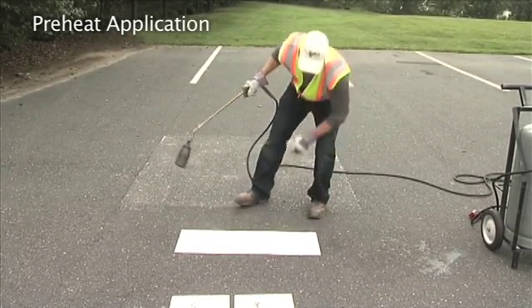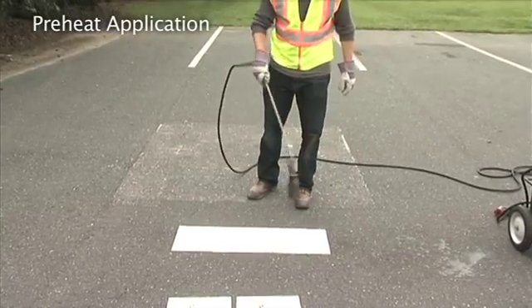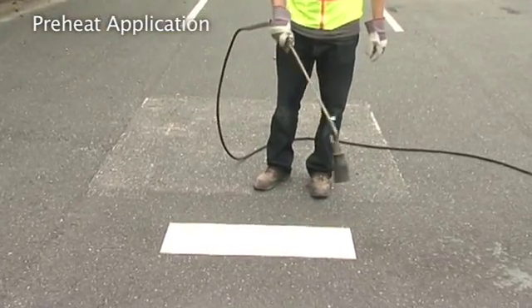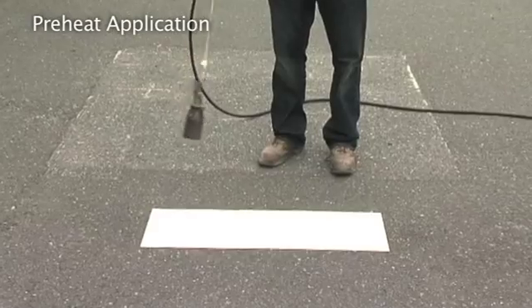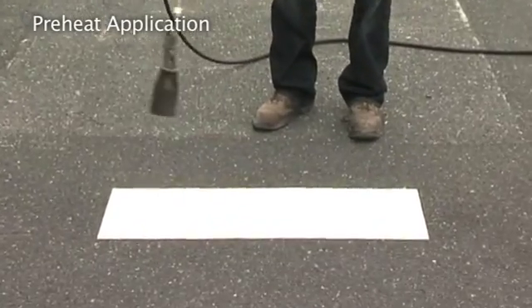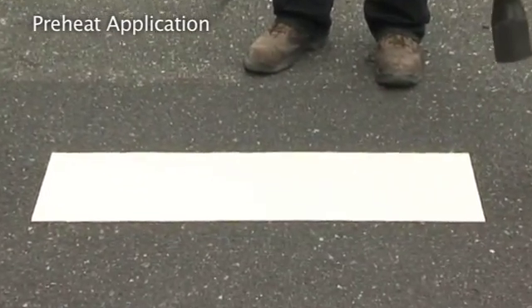Scaling back from the maximum output to the preset pilot valve setting, heat is applied to the material using a 2-foot wide sweeping motion 6 to 8 inches above the material. It's heated until the material softens and begins to conform to the pavement surface. Once it has a soft chewing gum appearance and the beads are approximately 60% embedded, enough heat has been applied. The material was allowed to cool for about 10 minutes.